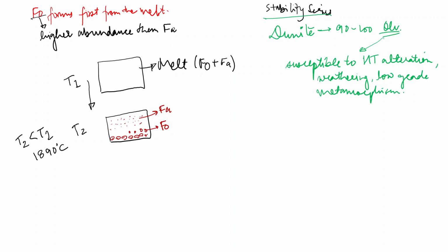The alteration involves the diffusion of hydrogen ions into the olivine structure, where they temporarily get attached to oxygen ions and release magnesium, Fe, and silicon ions from their sides. So what does alteration do?